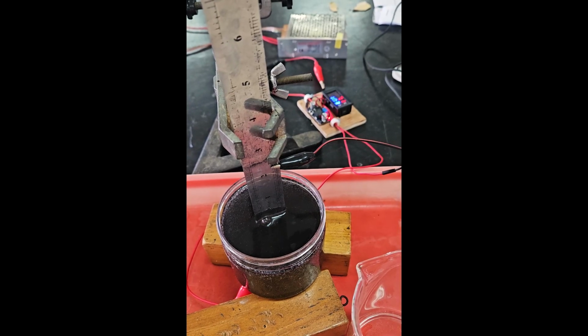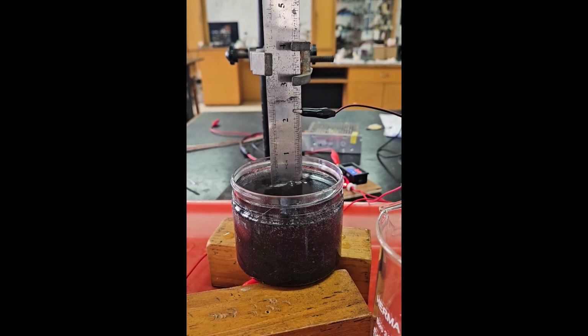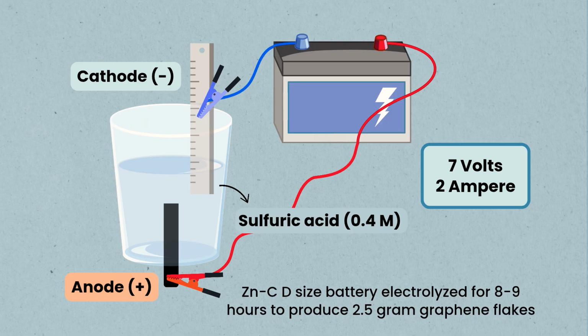In order to get the graphene flakes, a carbon rod from a used battery was utilized as the anode and a stainless steel roller as the cathode. The carbon rod was electrolyzed using sulfuric acid with a voltage of 7 volts and a current of 2 amperes.